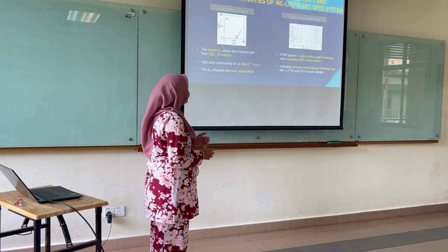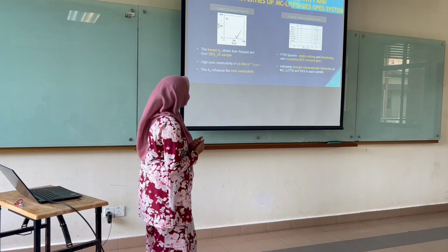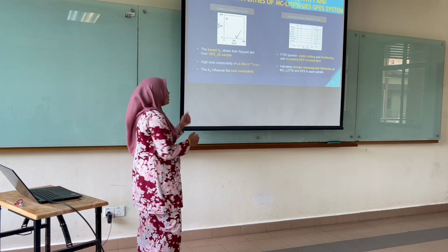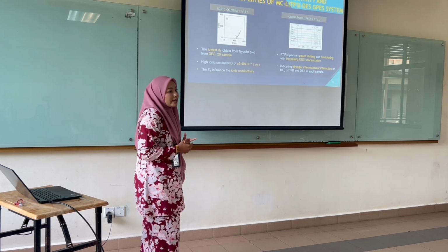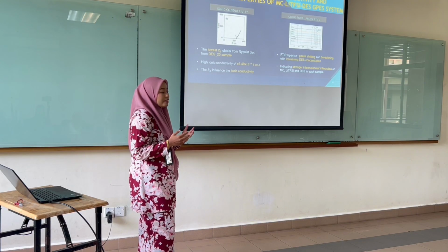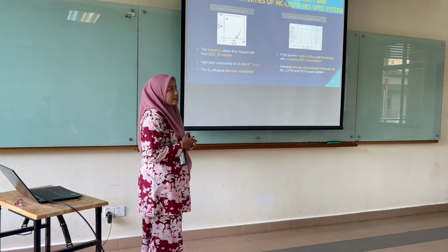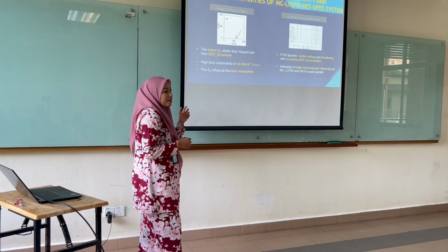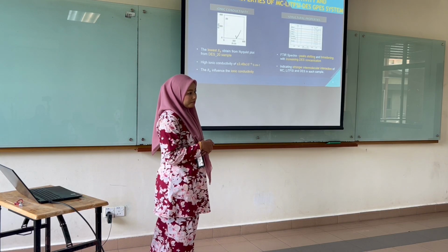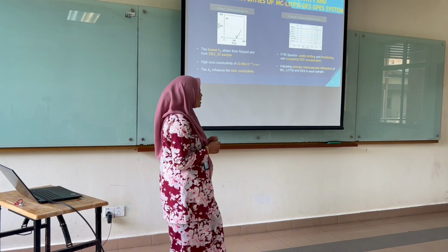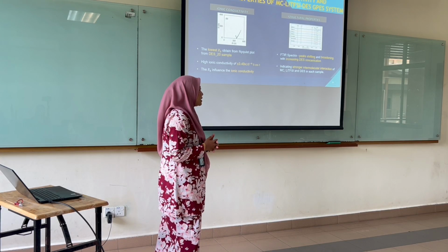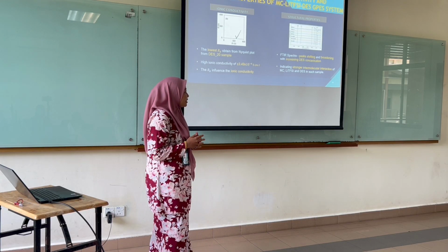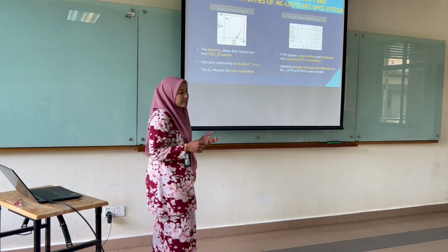Next, to summarize the correlation between ionic conductivity and structural properties of MC, LiTFSI, DS, and polymer electrolytes. As we know, the lowest bulk resistance obtained from the Nyquist plot is at DS20, which is the 20% DS sample, and it exhibits the high ionic conductivity, which is 3.49 × 10^-4 Siemens per centimeter. For structural properties, in the FTIR spectra, peak shifting and peak broadening increased with the DS concentration, indicating stronger molecular interaction of MC, LiTFSI, and DS in each sample.